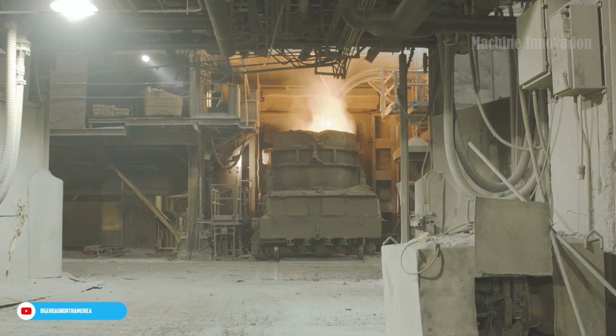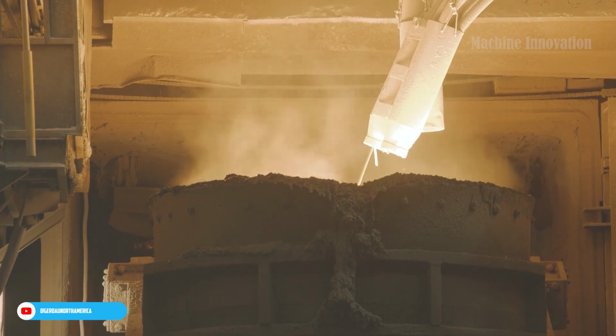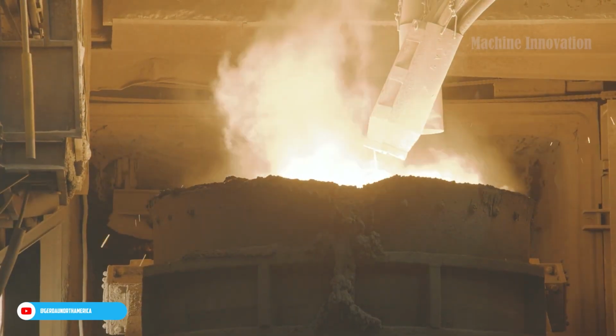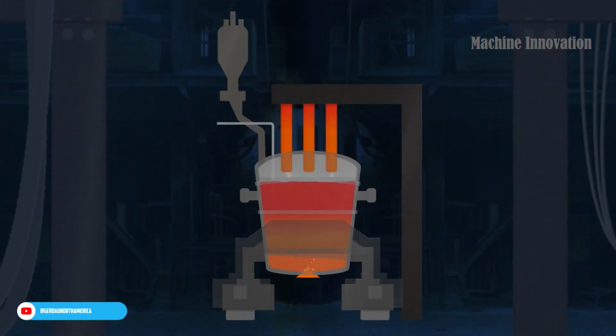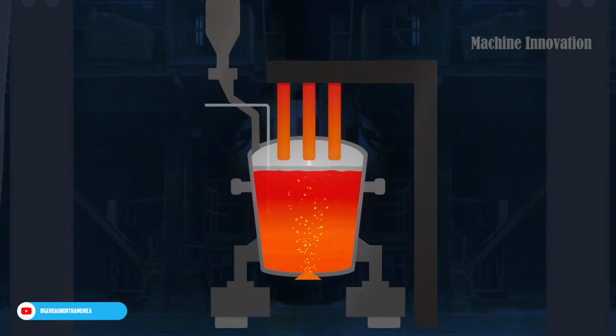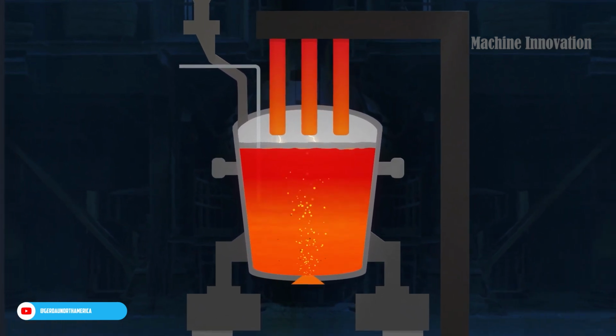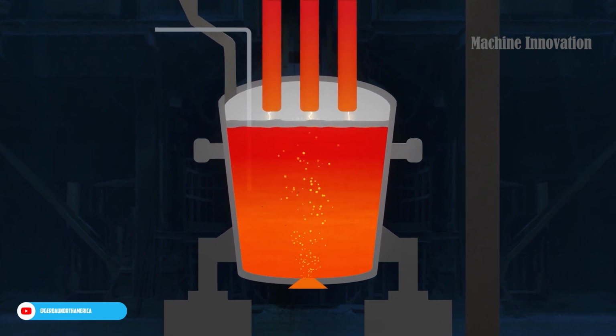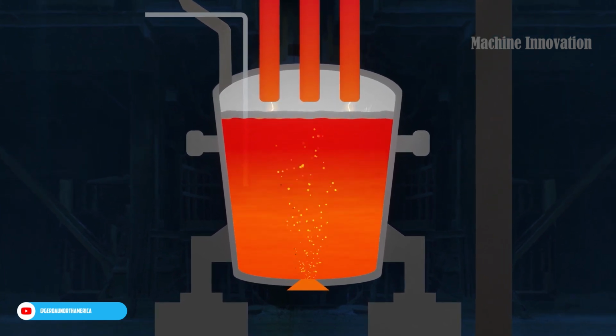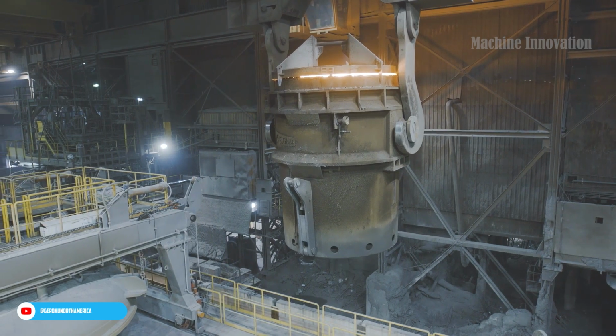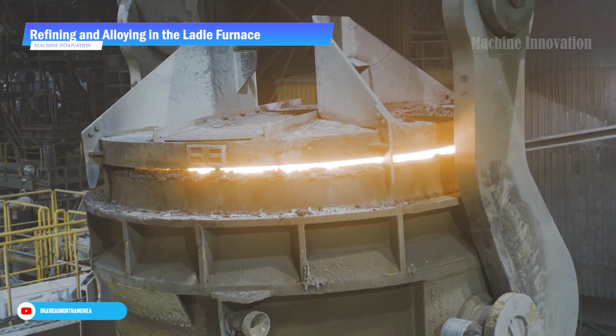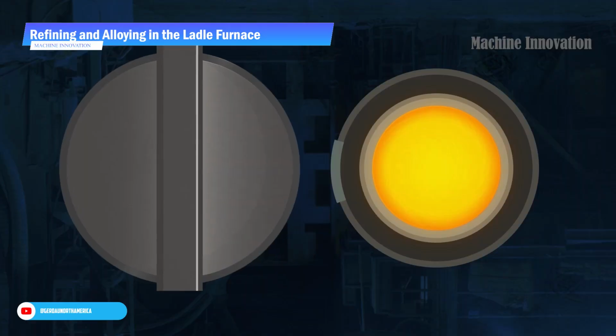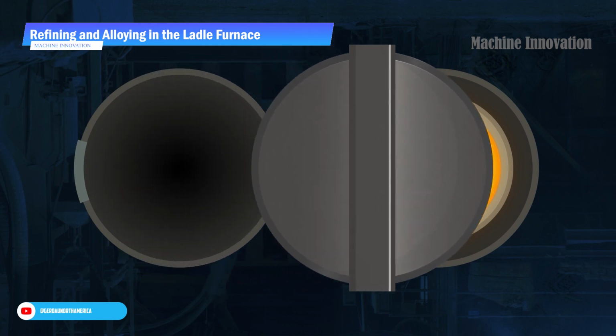During this melting phase, various impurities and contaminants are removed from the molten steel. The intense heat causes unwanted elements to separate, allowing the bulk alloy additions to be stirred evenly into the molten metal. This process ensures that the steel bath achieves a uniform composition, laying the groundwork for a consistent and strong end product. Following melting, the molten steel is poured into a ladle, a specialized vessel where further refinement occurs.